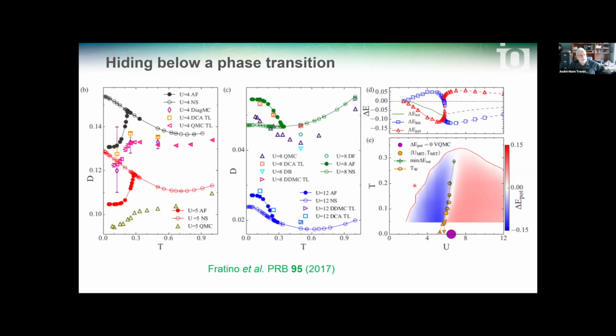If we stick to observables, we see that at small U, the double occupancy decreases as we enter the antiferromagnetic phase. So in reality, these are crossovers. If you look at the calculation that does not involve mean field, like this quantum Monte Carlo calculation, you see that there's no sharp drop here, but nevertheless, there's this fall. For larger U, it's the other way. You see that double occupancy increases as we enter the antiferromagnetic state.